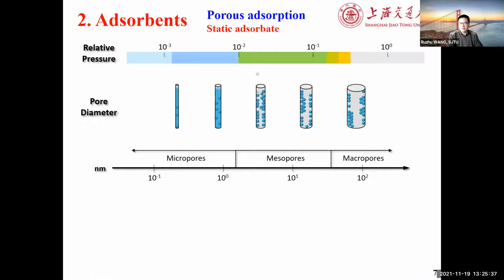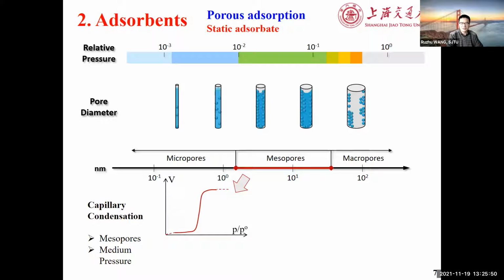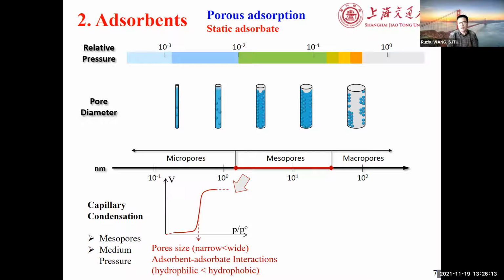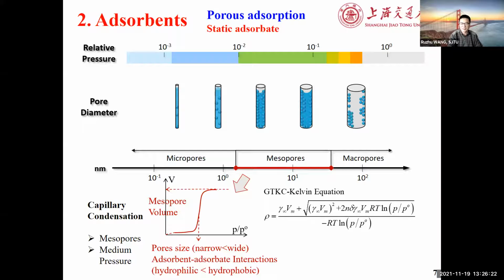And if we still increase the pores to mesopores, then as pressure goes higher, you could get capillary condensation. So at last, it's filled with all the liquid. So this shows we may have some kind of jump. At first it's a small mono-layer or double layer, but suddenly the pressure goes higher and you get this kind of jump. This is the capillary condensation, and it's important for the adsorbent. For some adsorbents, if there is only a very small pressure difference, you could get a very big difference in adsorption. This is why, currently, MOF material is so important for this kind of process.